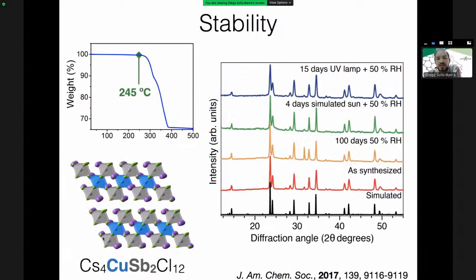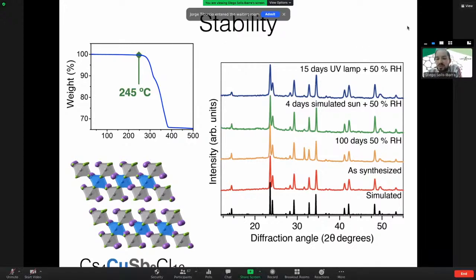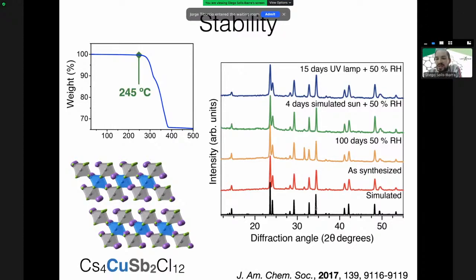We also show that the stability of this material was really great. It has a great thermal stability. If you want a material for solar cells, you want it to be stable to high temperatures because it's going to be heating while exposing to sun. And as compared to other perovskites, as I mentioned, we expose our material to relatively high humidities, and we also combine humidity plus illumination, like 4 days of simulated sun or UV and humidity, and the material stayed put in all of these conditions. We see no sign of degradation, which we think is a really great sign of stability, and it's a really great step towards that stability that we're looking for in these materials.